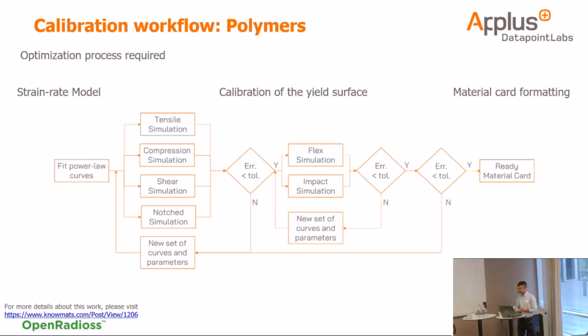So you start by testing the simple load cases that you have tested: tensile, compression, shear, and notch. Then you calculate the parameters, check if there is an error between your simulation and your experimental data, and you iterate again and again until you have validated these simple load cases. Then you move to the more complex conditions, which are usually 3-point bending and impact simulation. And then you adjust what you need according to the results until you have the proper solution.